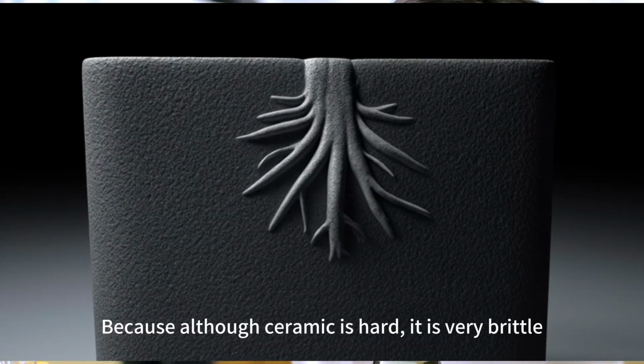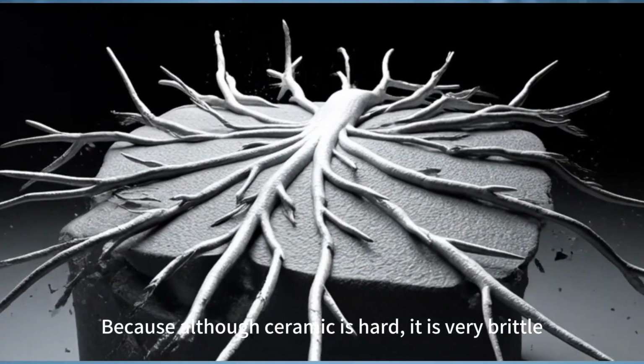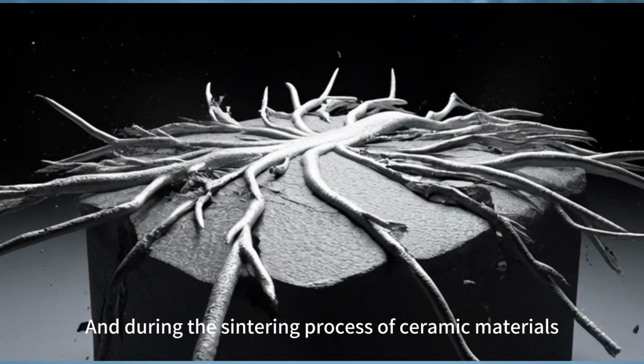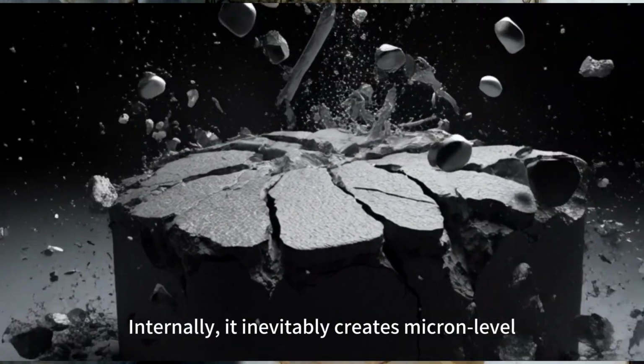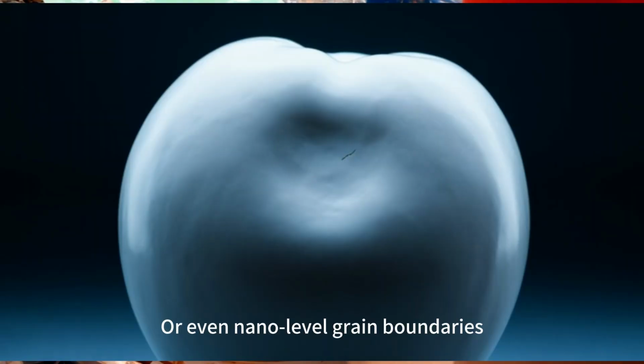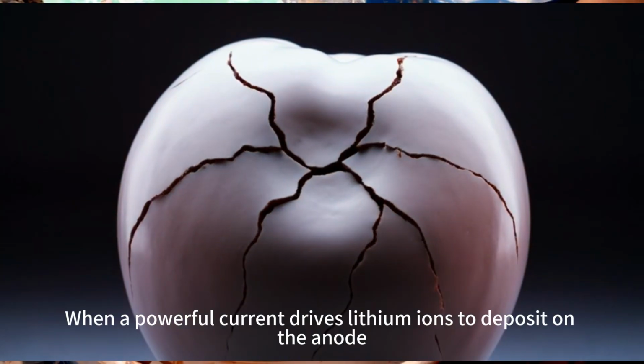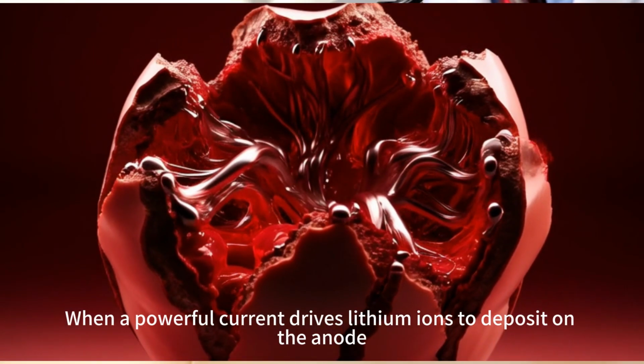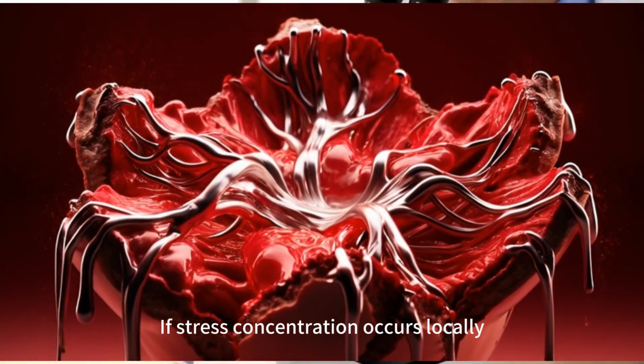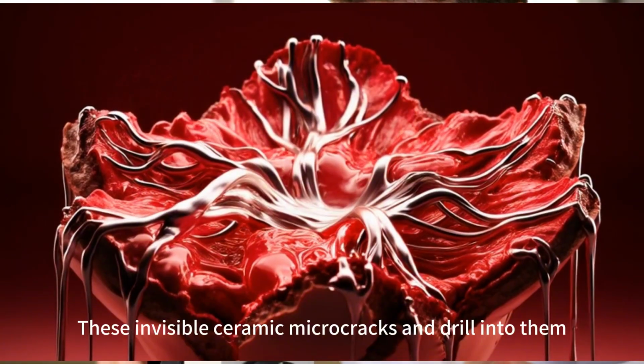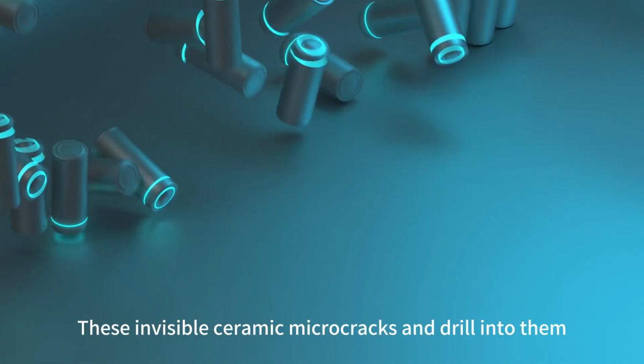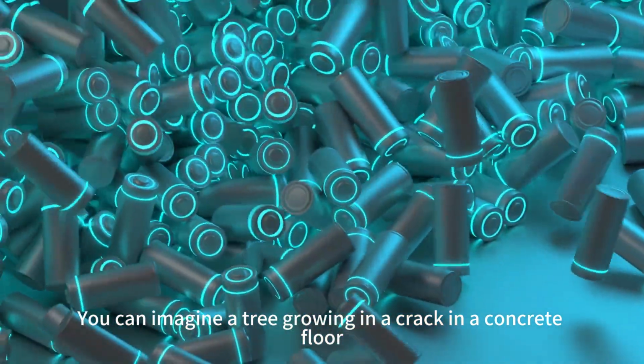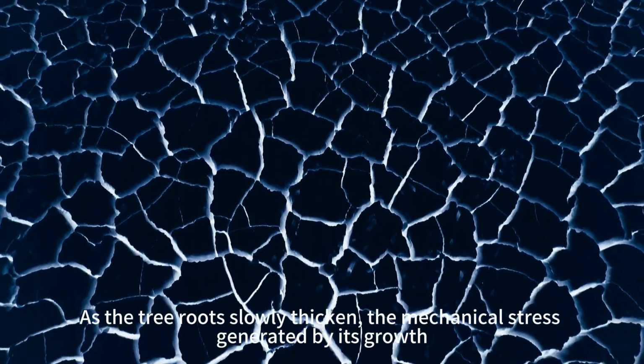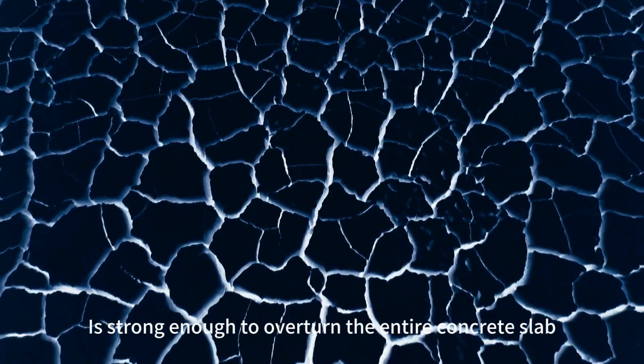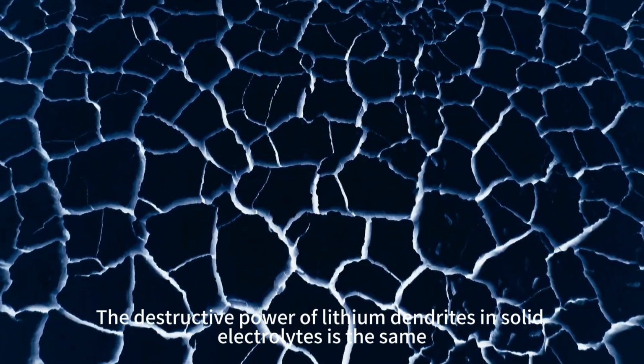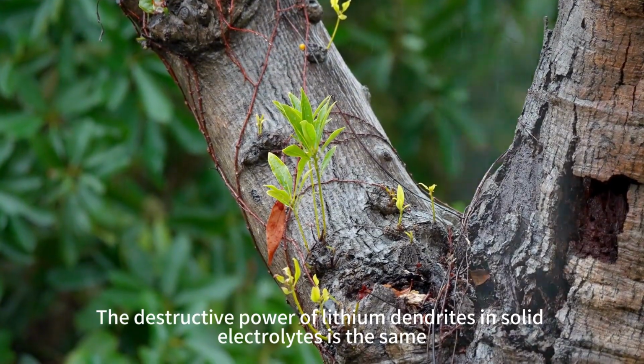Why does this happen? Because although ceramic is hard, it is very brittle. And during the sintering process of ceramic materials, it inevitably creates micron-level or even nano-level grain boundaries and microcracks internally. When a powerful current drives lithium ions to deposit on the anode, if stress concentration occurs locally, lithium metal will follow these invisible ceramic microcracks and drill into them. You can imagine a tree growing in a crack in a concrete floor. As the tree roots slowly thicken, the mechanical stress generated by its growth is strong enough to overturn the entire concrete slab. The destructive power of lithium dendrites in solid electrolytes is the same.